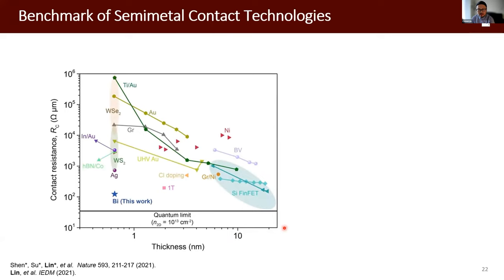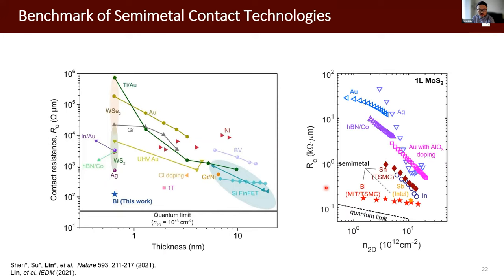Finally, let's compare different technology. So I showed you this figure earlier. Contact resistance versus thickness, our work with bismuth contact indeed shows almost one order of magnitude better contact resistance than the previous work. And we can also show contact resistance versus 2D carrier density. There are a family of semi-metals, including bismuth, antimony, tin. They all show the best performance among all different contact technologies. And our technology target is around 100 ohm micrometer. So the bismuth technology is very close for practical application.